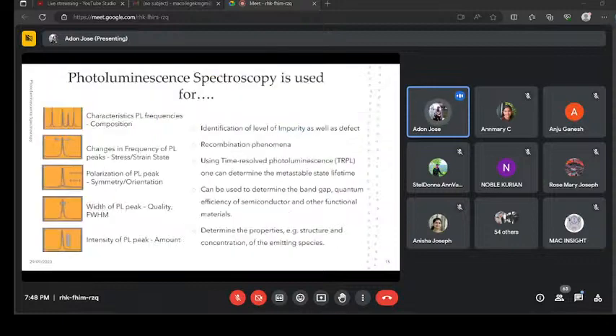We can identify the lambda as 520 nanometer in this case, and 620 nanometer in this case. In each case, whenever the size is increased, we can easily identify its band gap from the spectrum we have observed from the photoluminescence spectroscopy by simply substituting the lambda value in the E equals hc by lambda equation. So the other technique we can identify is the impurity levels and defect detection.